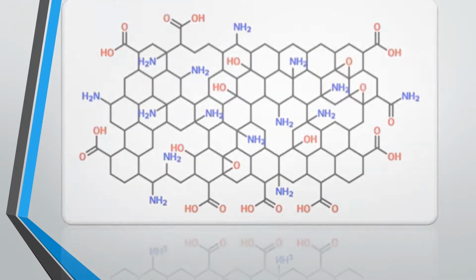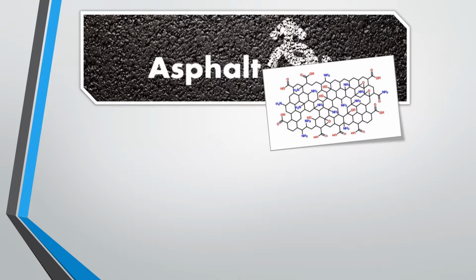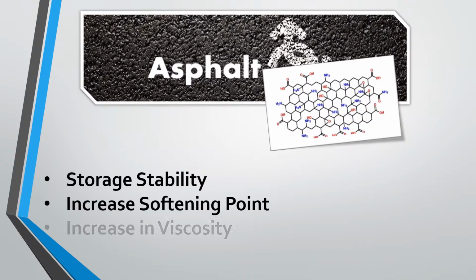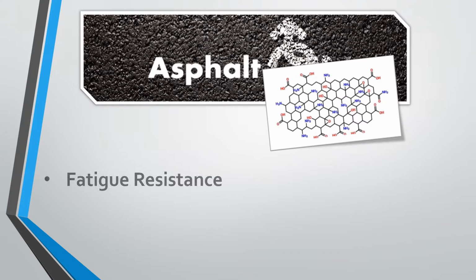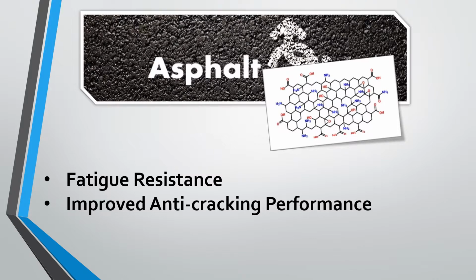There are many studies about the possible incorporation of graphene oxide in different asphalt mixes. The asphalt with GO exhibits better storage stability and an increase in softening point and viscosity. It improved the fatigue resistance of ordinary asphalt and exhibits anti-cracking performance and high resistance to rutting and shoving.